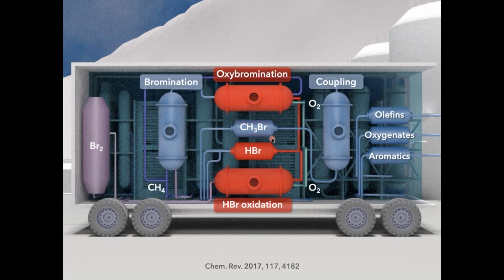This technology, both in the bromination step and in the coupling step, has one issue, and this is that hydrobromic acid is released. So in order for this process to be economical, all the bromine will need to be recovered back into the main bromine, and this can be done by HBr oxidation. So you oxidize HBr into bromine, so you have a closed loop of the halogen.